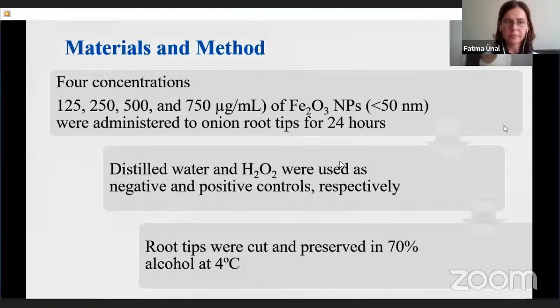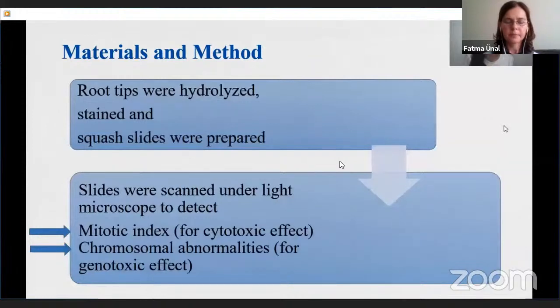Yes, I would like to talk about my own study. I used four different concentrations of iron oxide nanoparticles. Size is smaller than 50 nanometers, and they were administered to onion root tips for 24 hours. Distilled water and hydrogen peroxide were used as negative and positive control, respectively. Root tips were cut and preserved in 70% alcohol at 4 degrees centigrade. Root tips were hydrolyzed, stained, and squash slides were prepared. Slides were scanned under a light microscope to detect the mitotic index for cytotoxic effect and chromosomal abnormalities for genotoxic effect.